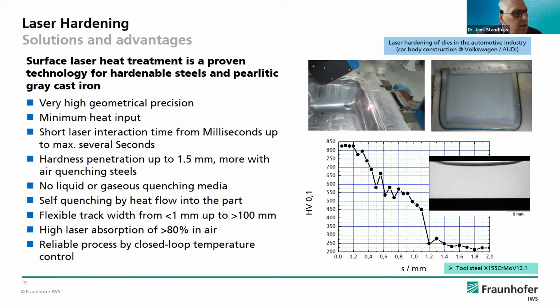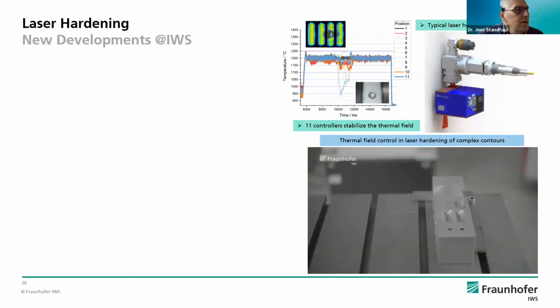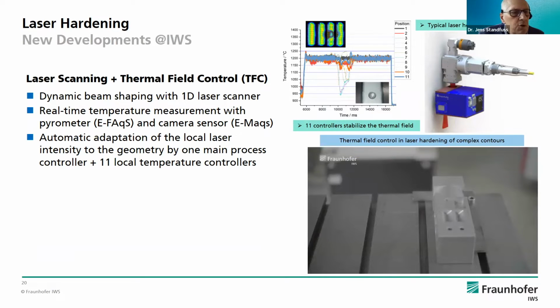Rockwell. And you have a very efficient process because the absorption on the part is quite high, so it's a very good process. But what you need is some systems to control this and to integrate and be flexible, and also use the flexibility of such a process. And what you need is two things. You need a beam forming to shape the laser beam and adapt it to the part, and you must control the temperature, the heat input, depending on the geometry and the heat conduction of the part. And both can be offered. There are some developments, some real-time measurement sensors to control the process parameters, and this is connected to a beam forming to adapt the beam.